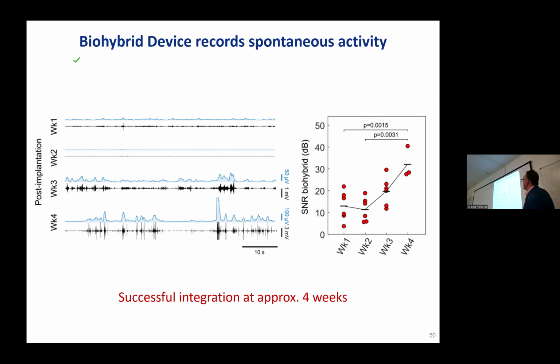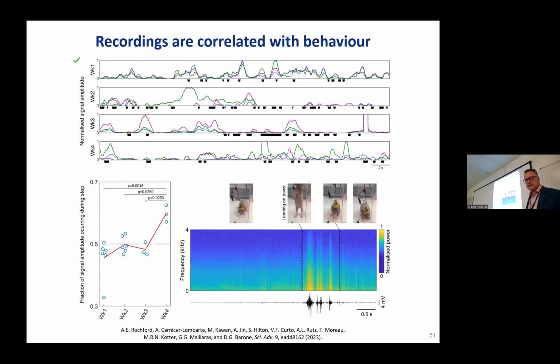And then these are the recordings of spontaneous activity. So recordings from one electrode shown here, week 1 to week 4. See, week 1 and week 2, very little signal. But then from week 3, you already start seeing nice muscle activity, which becomes very well defined at week 4. And you can record these command signals very nicely. You can also correlate them with behavior, and they correlate very nicely, but that's secondary.